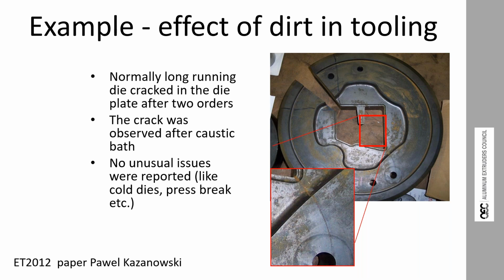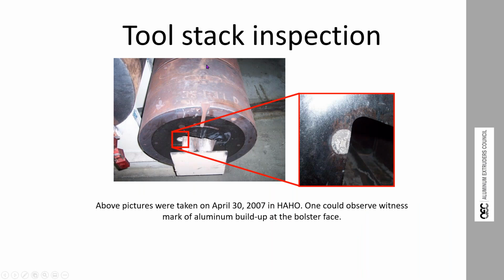We found there was pretty much nothing wrong with the tool steel, which was a bit of a surprise. There was a lot of hemming and hawing and scratching of heads, but this die life was down dramatically from the normal die life. And you could see it happened at a particular day. After a particular day, there was a drop in die life. And we spent some time chasing it, and in the end, this was it. I actually took this picture. This is about the size of a nickel. It happened to be in exactly the right position to put the die plate into a teeter-totter and create the stresses which caused those dies to crack.